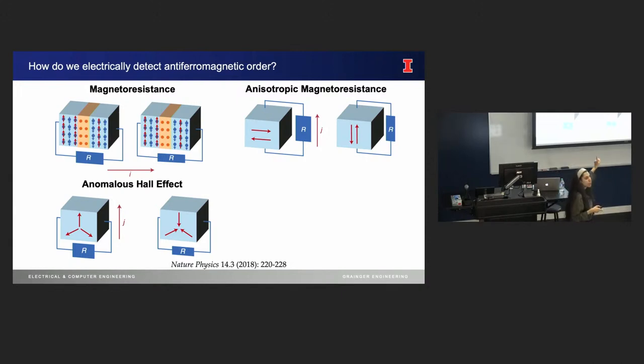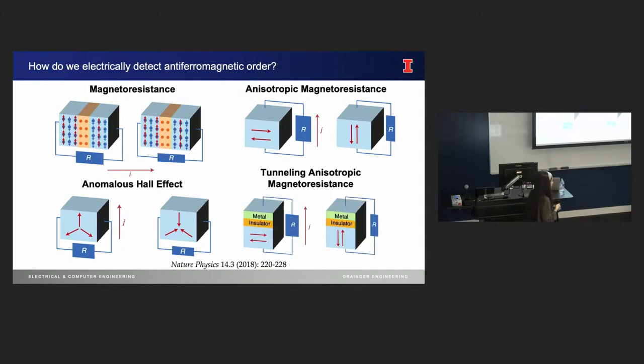Now this is the anomalous Hall effect. So what is anomalous about it? Well, what typically happens is that this is an odd function, and therefore you're not expected to get this in the case of antiferromagnets. It should cancel out. But interestingly, in manganese tin, the material of choice today, this phenomenon has been experimentally measured. It occurs in this material, so it's a very powerful tool to look at Mn3Sn.